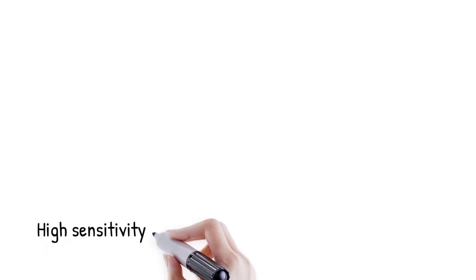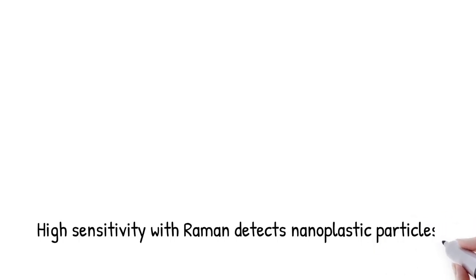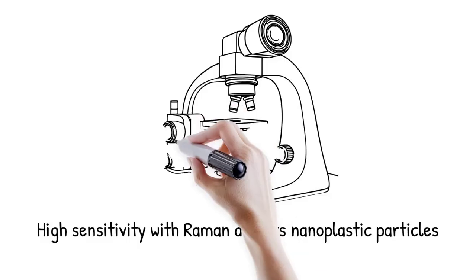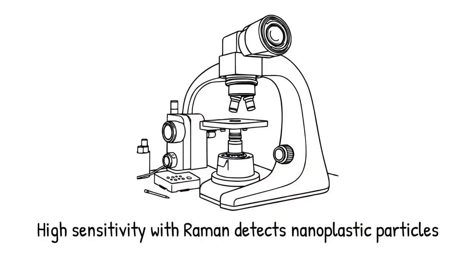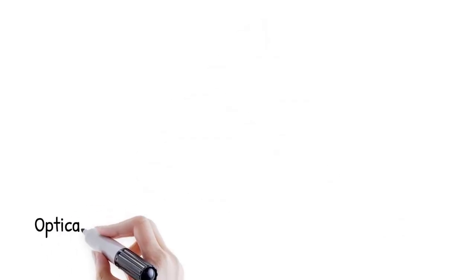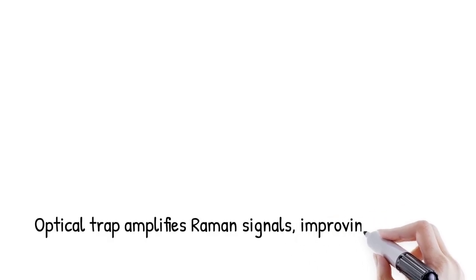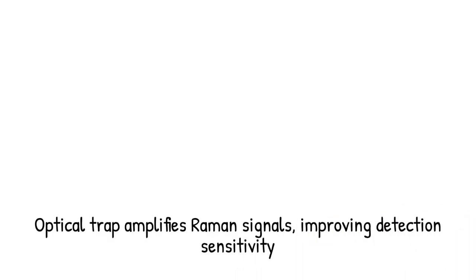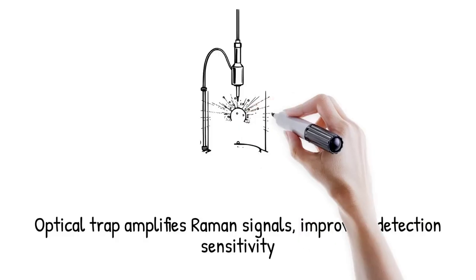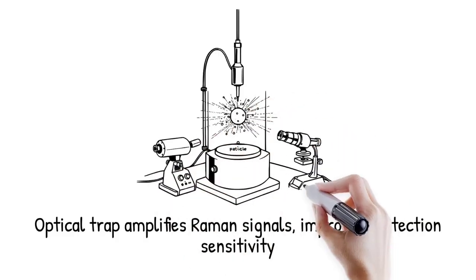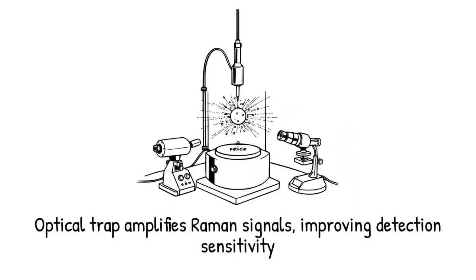By combining force-based concentration with sensitive Raman readout, the platform achieves limits of detection down to single digits of nanoplastic particles per milliliter. Signal-to-noise ratios above 20 dB are maintained even for particles below 100 nm diameter. The optical trap enhances local particle concentration by factors of 10^3 to 10^4, effectively amplifying weak Raman signals. Rejection of autofluorescence and thermal background further improves sensitivity.